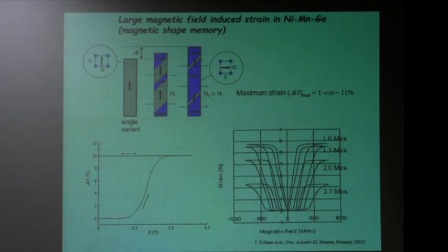So if you do these kinds of measurements by applying stress, here we have 1 megapascal to 2.5 megapascals of stress, which are applied while we are applying the magnetic field, okay? So let's try to visualize what we're doing here at 1 megapascal. We start here, we go up, just as we're doing here. And since we've applied a stress, this doesn't go straight back, but it goes down because our mechanical stress forces us to go back to the original single variant state.